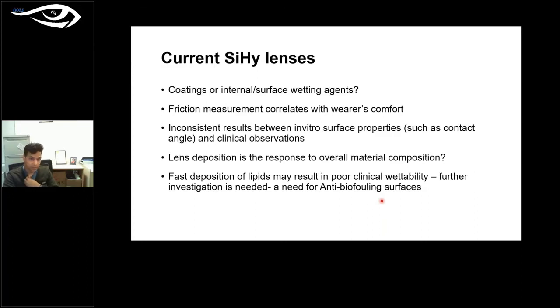We have also seen that lens deposition could be a response to the overall material composition rather than just the surface coatings. The fast deposition of lipids may result in poor clinically wettable contact lenses, so this requires further investigation. One of the things that we may require is a lens with anti-biofouling surfaces. That means surfaces which discourage any kind of deposition on the lens surface.